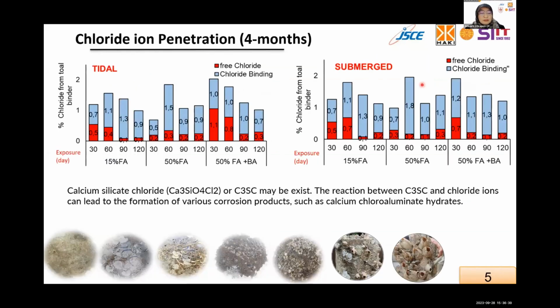And here for 4 months observations, chloride penetration at the depth of 5 centimeters of concrete was analyzed. Free chloride ion, here the red one, in all specimens in tidal area were found very much more than in submerged area. And we found that the barnacles are attached to the surface and also increasing their populations. This is like pros and cons, because this may cause increase or decrease of ion penetration to the concrete.